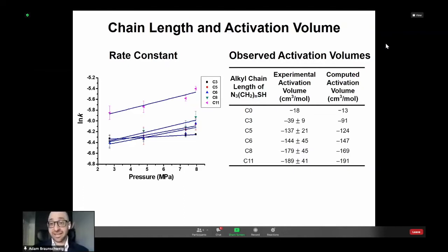And you see a near perfect match until you get to about C3. And this actually helped confirm what we were thinking. So in silico, in the Hauck group, what they do is they consider perfect monolayers. However, in the self-assembled monolayer community, we know that chain lengths below about C5 no longer order together.